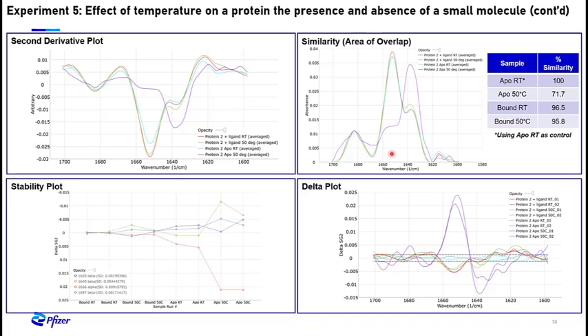It is also obvious here that the protein complex at 50 degrees centigrade has also gained some beta sheet content as well and lost a little alpha helicity. But considering the heat stress, it's not that much. The ligand has really protected the protein from denaturation. Below is again the delta plot, highlighting the regions of change in the spectrum with significant change based on whether it goes above or below the dashed line. To the left of the delta plot, we see the same drama with the heat-treated apoprotein.